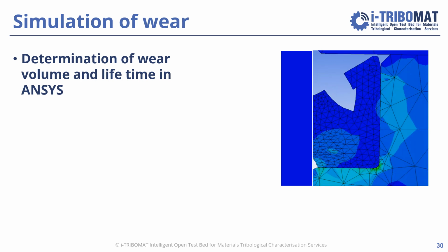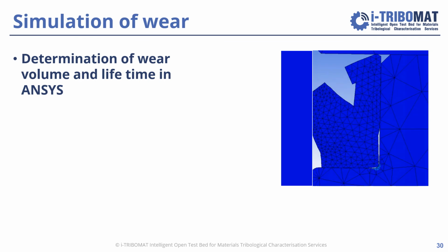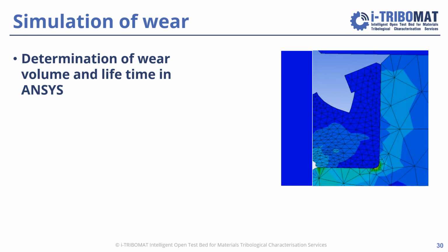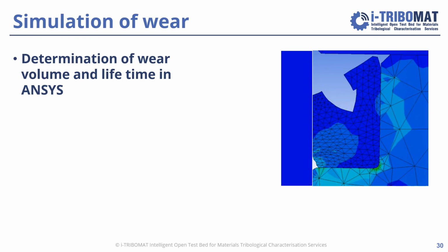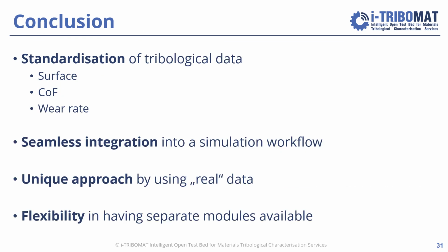And we're not just detecting where wear occurs, we are actually taking away elements that take part in the simulation and carry load and stress strain information. As a conclusion, I would like to point out that we have achieved the standardization of tribological data that we measure experimentally of the surface, of the coefficient of friction, and the wear rate. So we have defined the file format, we have defined how we process the experimental data, and then we've integrated that in a seamless way into a workflow of the simulation.